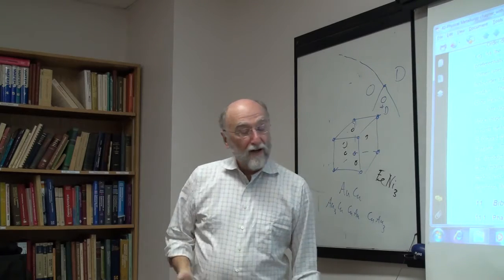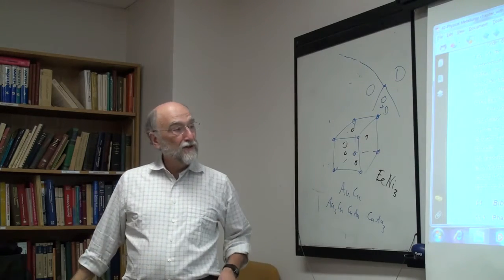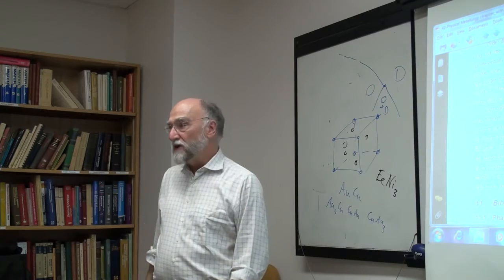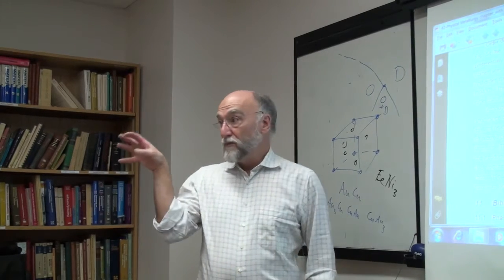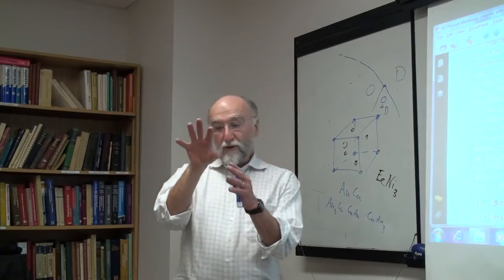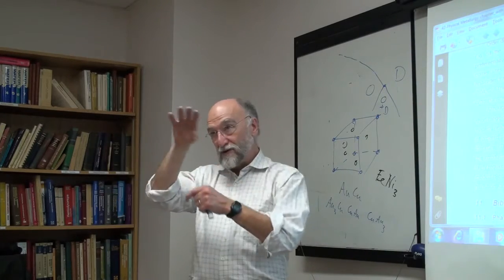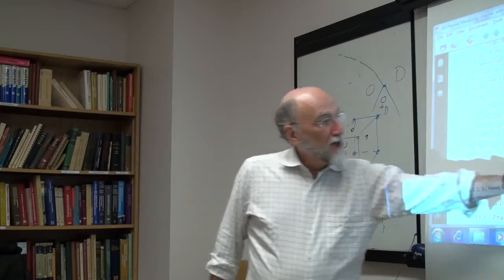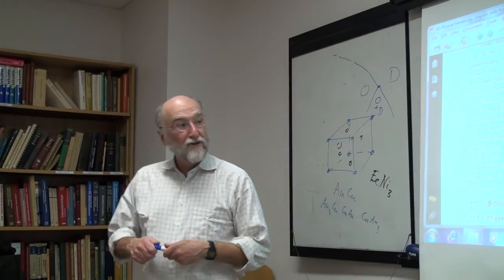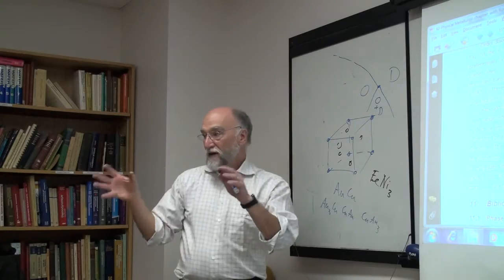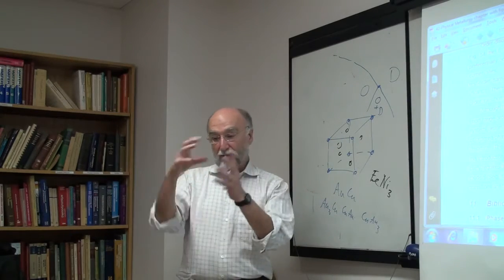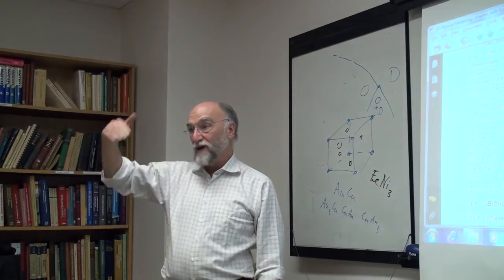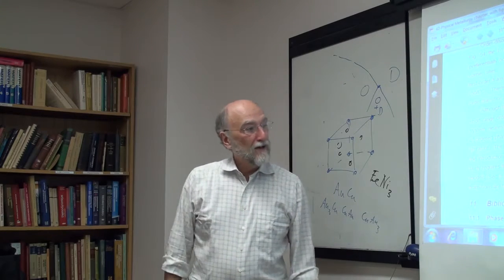The quadruplet model that I talked about in the ionic systems, the quasi-chemical model, is one example of a cluster variation method in which the clusters are quadruplets. Remember what we did: we distributed the quadruplets over quadruplet sites, and then we took the next step down, assuming that the pairs are randomly distributed, so you have three levels. In the general cluster variation method, you can have several different kinds of clusters. You can have clusters which are octahedra, tetrahedra. They're distributed over octahedral and tetrahedral sites, taking into account the geometry of the face-centered cell. And then you have different levels going back down to quadruplets, pairs. And it becomes mathematically extremely complicated.